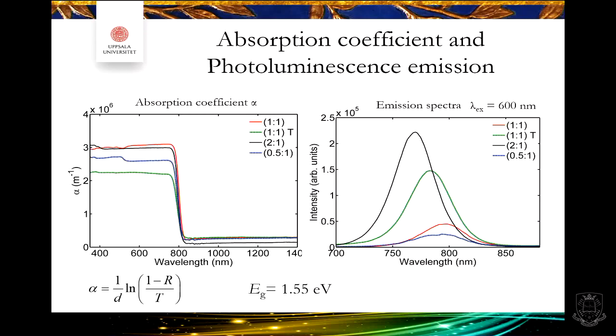So it's rather easy to model that in different ways and look at what my band gap is, but approximately the band gap in this material is 1.55, which is also actually a little bit more suitable for a single junction solar cell. Otherwise it's usually shifted a little bit.